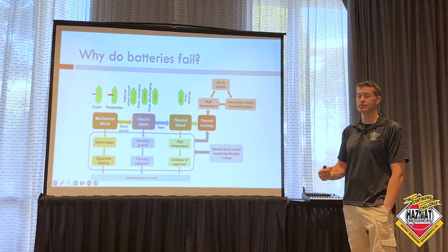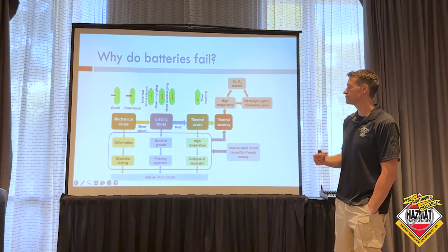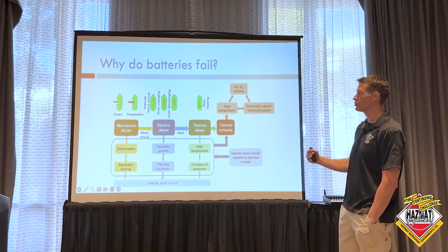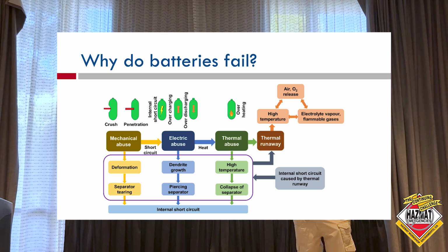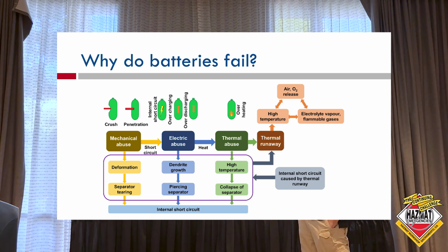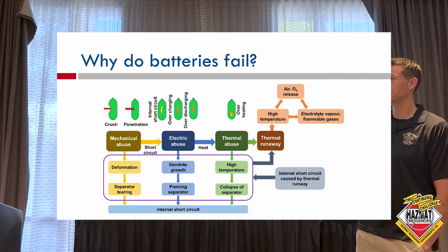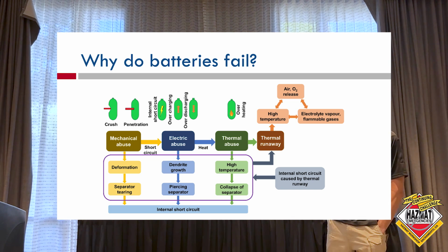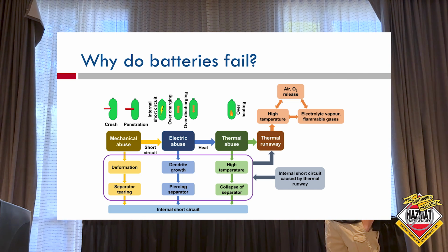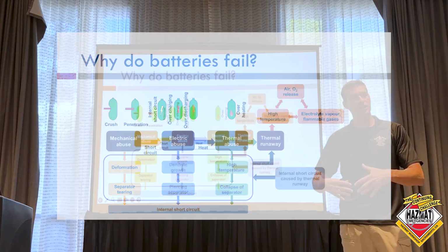So how do they get, what do we call insults, right? We talk about insulting, and that's kind of the term in the industry. We call it what happens to batteries. So mechanical abuse is one form of insult. That's the easiest one, right? That's smashing it on the table, puncturing it. Don't put a finishing nail through one. We did that. That wasn't good. It works though, really good. It just goes into thermal runaway right now. Deformation, dropping it, crushing it, all those things, right?